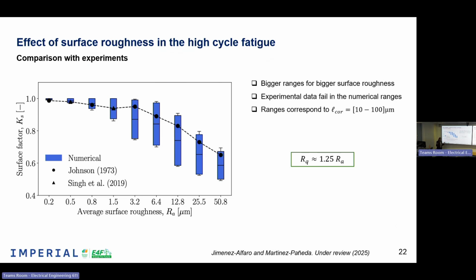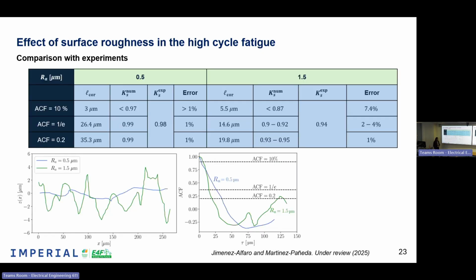With this, we have an approximation, but imagine if we know the correlation length. This is what we are going to do now. Here in this table, we also have the experiments of Singh et al., but in this case, they gave to us the surface profile, this kind of graph that is very typical in the papers for surface roughness. And with this, we have just extracted the data, we have computed the ACF, and using the three criteria, we have got the correlation length.